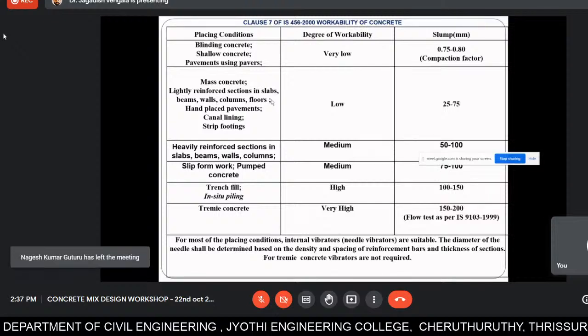You can see that particularly we go for the 0 slump, but to differentiate, we just measure the compaction factor test for 0 slump. So usually a 0.75 to 0.8 compaction factor you achieve for pavement concrete or whatever. This is a very low degree of workability. And for mass concrete and canal linings and other beams, walls or lightly reinforced sections, we go for the low degree of workability, wherein the slump is between 25 to 75. And heavily reinforced sections, medium workability, that is between 50 to 100, and pumped concrete is medium again, between 75 to 100, and trench fill, in situ piling works and all, the high workability you require is between 100 to 150, and for tremie concrete, you just pour the concrete there, very high workability, 150 to 200.